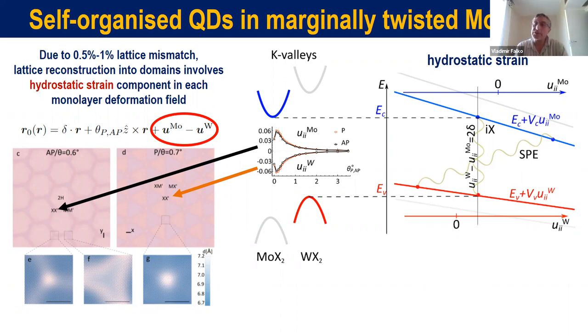And when the hydrostatic strain component in these two layers has an opposite sign, then the band edges in the two layers move against each other. In fact, for the conduction band edge in the molybdenum layer, it goes down in the domain wall corners. And for the tungsten layer, the valence band edge at the K point goes up.